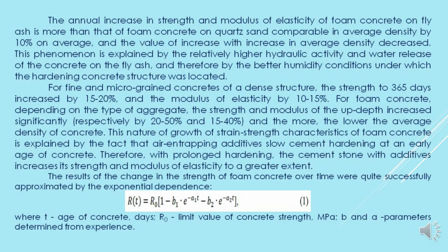For fine and micro-grained concretes of a dense structure, the strength to 365 days increased by 15 to 20% and the modulus of elasticity by 10 to 15%. For foam concrete, depending on the type of aggregate, the strength and modulus of elasticity increased significantly, respectively by 20 to 50% and 15 to 40%, and the more, the lower the average density of concrete.